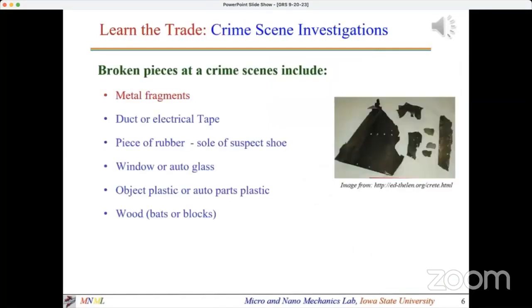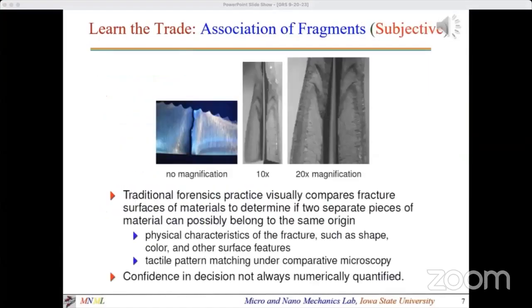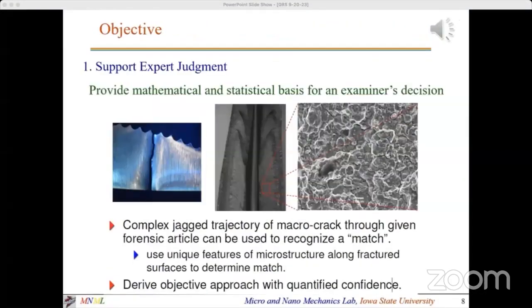Reviewing the ongoing work of forensic scientists, we found that forensic fracture matching covers many classes of materials found at a crime scene. Here, we focus on metal fragments that undergo brittle fracture with limited deformation, so we can have a near locally planar fracture surface that could be easily imaged with a 3D topographical microscope. A key finding is that the association of fragments is subjective and the confidence in the decision is not identified. So, experience does not substitute for demonstration of accuracy. We want to support the expert judgment by providing a mathematical and statistical basis for the examiner decision using the topographical details of the fracture surface.